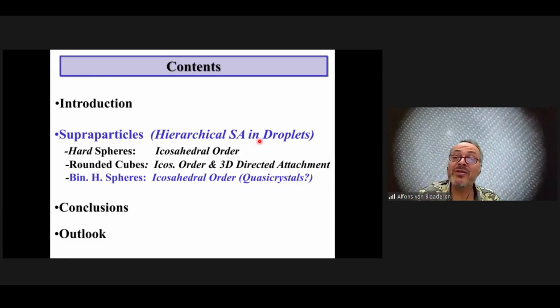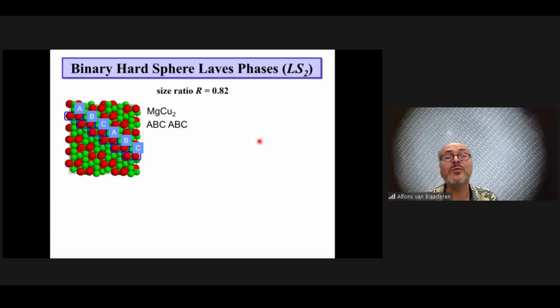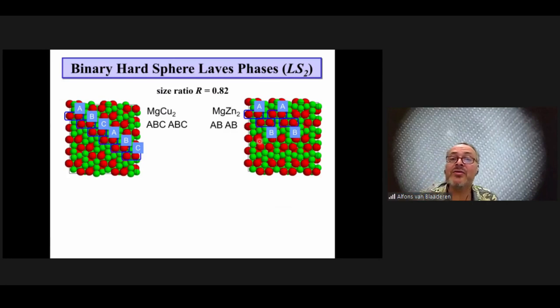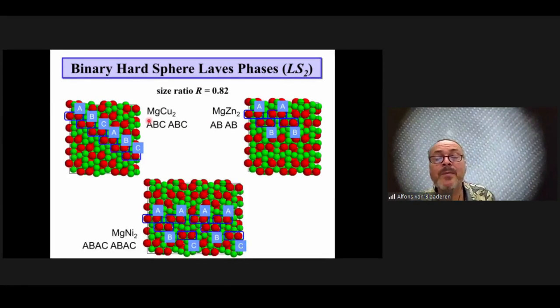So what now happens if we want to look at a binary crystal? What we chose is a size ratio of the hard particles of 0.82. And I'm not going to go into the details, but these are called Laves phase crystals, and you find them in metallic crystals. But very similarly to the hard sphere case, when you have a kind of ABC stacking of these binary layers, that's a very interesting structure. That's the equivalent of a hard sphere's FCC, but here it's magnesium copper 2.